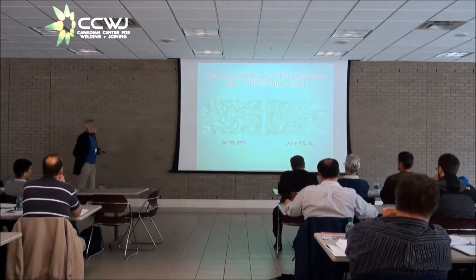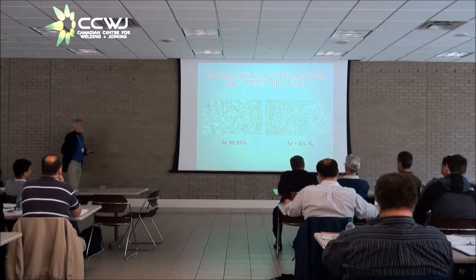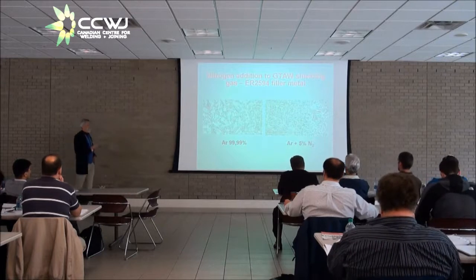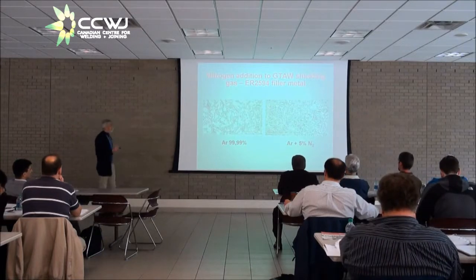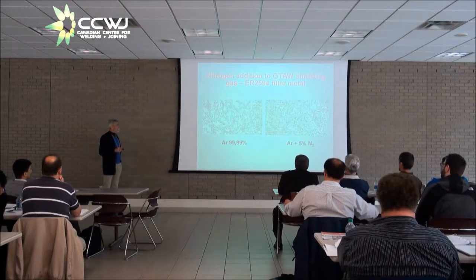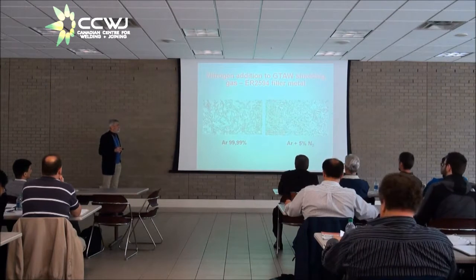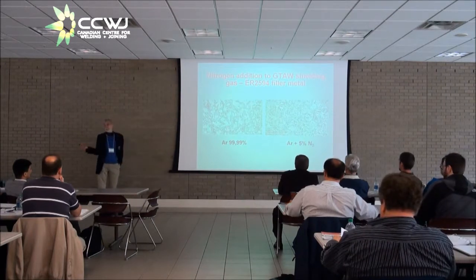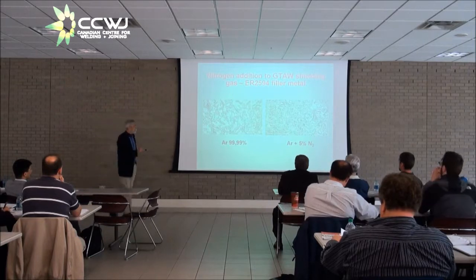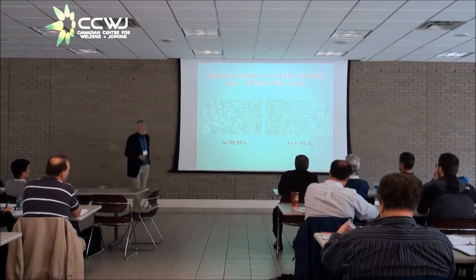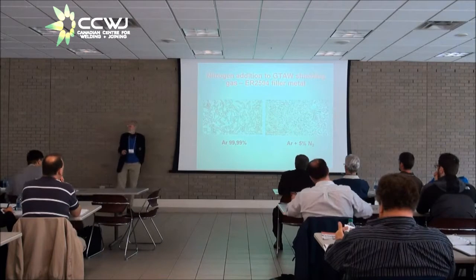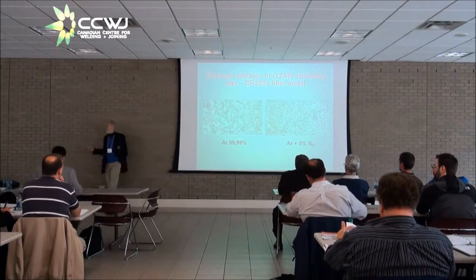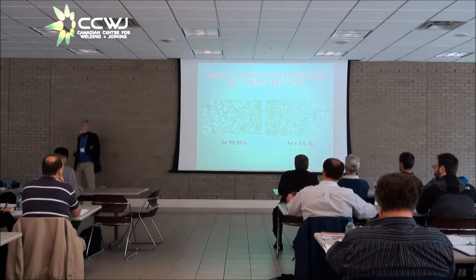This is looking at gas tungsten arc welding with pure argon versus 5% nitrogen. With pure argon, you'll still get pretty good impacts, but you've got these pretty large ferrite areas which are at risk for getting nitride precipitation. Whereas when you add the nitrogen to the shielding gas, you have very little in the way of large ferrite areas, and therefore much less tendency to get all the nitrides.